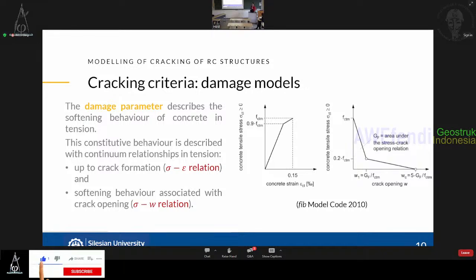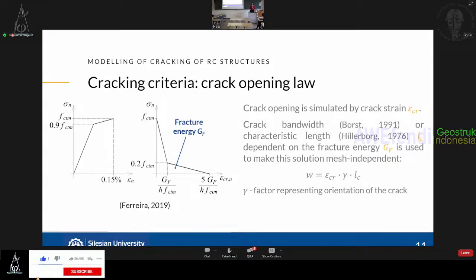And then once the element is cracked, we are observing the softening behavior, which is related to opening of the crack. However, the use of this model directly is not very feasible because we don't really have a crack which is opening. That is why we are operating rather with the use of the so-called crack strain, which has already been discussed as well. So using this crack strain, we are able to recalculate the crack width, knowing the value of this crack strain and the size of the element, and also to avoid the problem of mesh dependency. We are using this parameter, which is called crack bandwidth or characteristic length. And this is a parameter which is related to the fracture energy. So it's one of the, let's say, inherent properties of the material that we are studying.